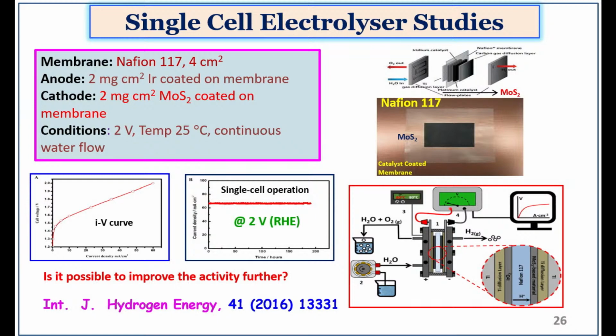A non-noble metal based material producing 65 milliampere is good for me. But when you compare with platinum, it produces 1 ampere, almost 15 times higher current density. But platinum is a noble metal, and its cost is too much.